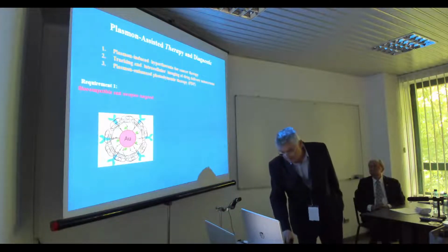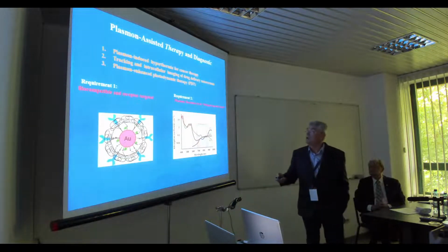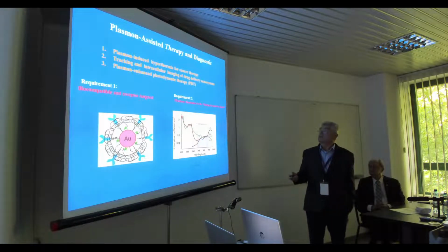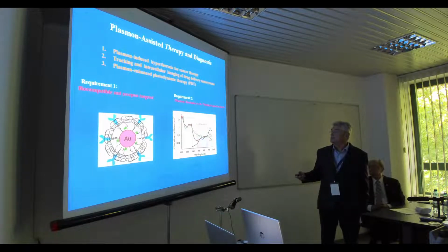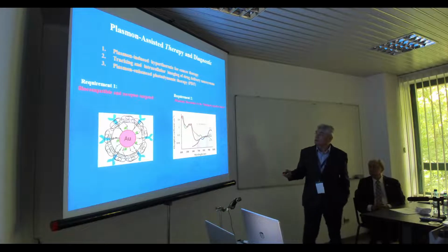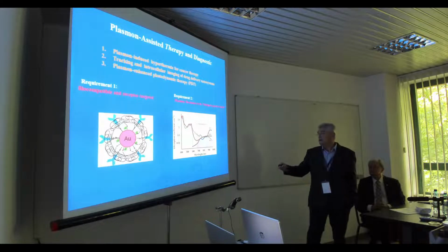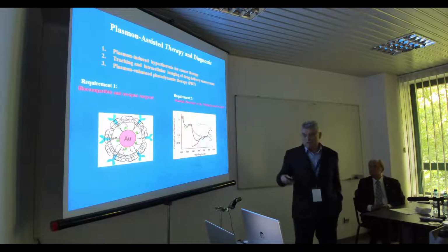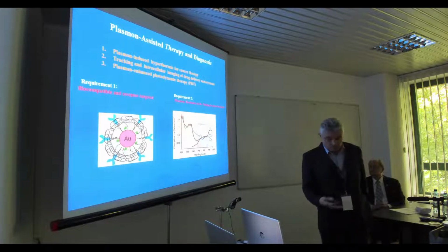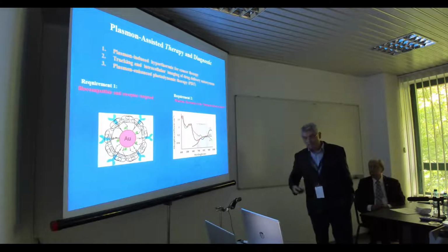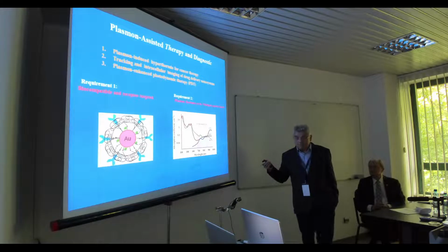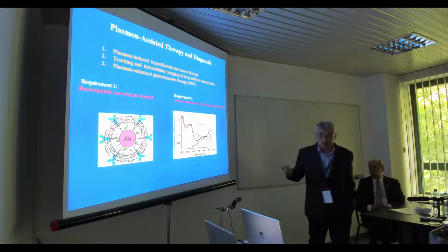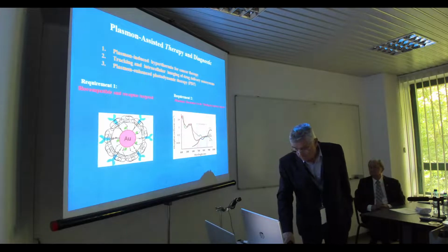This is one example. In my research group, we try to control the resonance of the nanoparticle to bring it inside this window called the biological window, because light in the near infrared, from 700, 900, 1000 nanometers, is more transparent, and the background from the tissue is lower. If you think of applying it in real life, it's better to work with nanoparticles which have resonance in this window. This is our interest. Now, this is about the introduction.